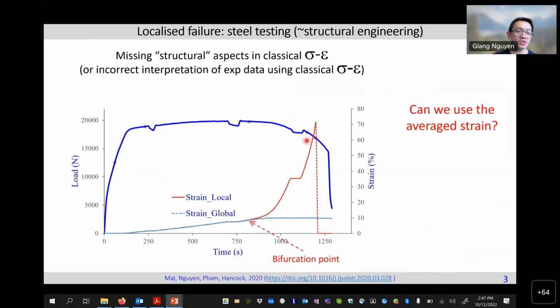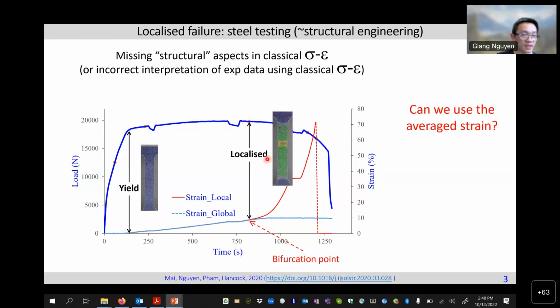And if we plot the strain at different locations or different areas, the global strain, that is the macro average strain, the light blue curve here, and the strain in the localization zone, the zone where cracking in the end happens, we see something different here. We plot the strain evolution with time. So we see the departure of these two strains. At this point, it's called the bifurcation point. So still, we have the question, can we use the average strain here? I will try to answer later. Okay, so yielding in this case will lead to homogeneous deformation, but after being localized, the problem would become much more complicated.